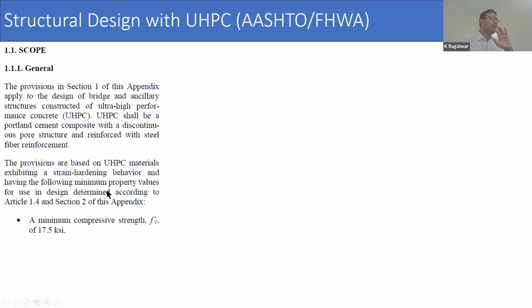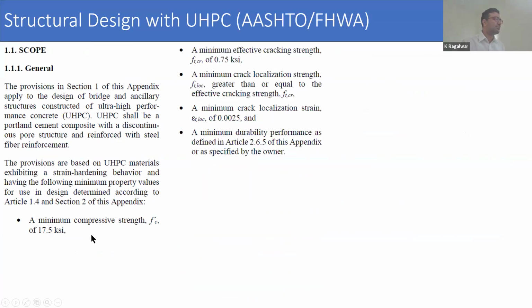So I'm going to talk about how AASHTO and FHWA define material parameters, because to use these guides, you need to have minimum specifications in the materials that can define it as UHPC. So the minimum compressive strength of 17.5 ksi, a minimum effective cracking strength of 0.75 ksi, a minimum crack localization strength greater than or equal to effective cracking strength. So that is a requirement.